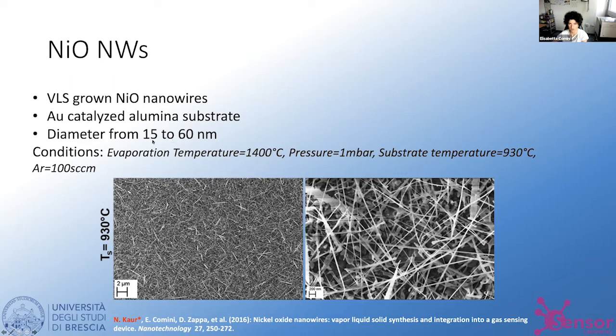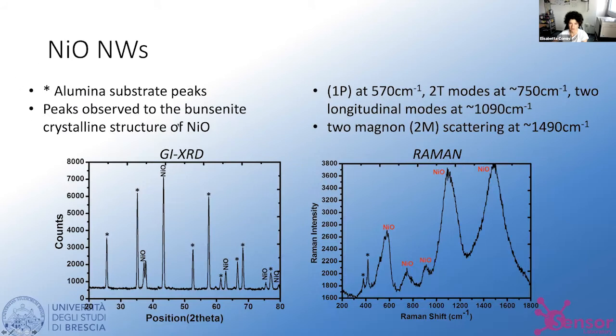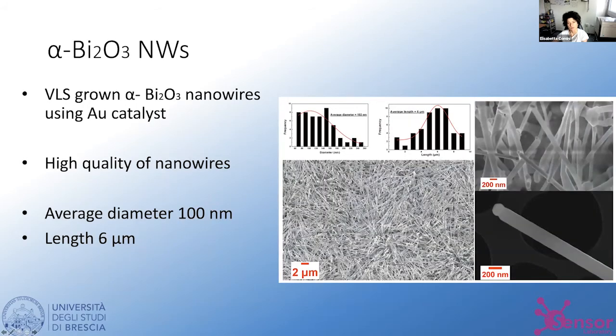The diameter of the nanowires is from 15 to 60 nanometers. And if we have a look at the crystalline phase of nickel oxide, we can see that it is the bunsenite structure, which is also, I mean, the presence of nickel oxide is confirmed also by Raman measurements.